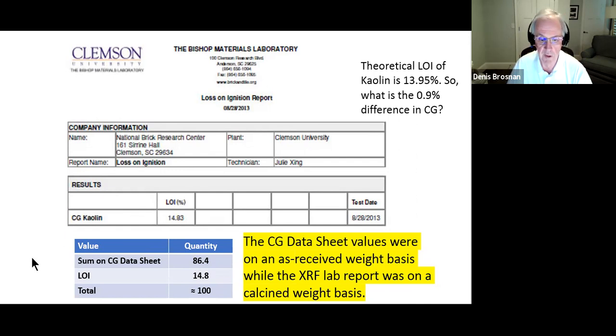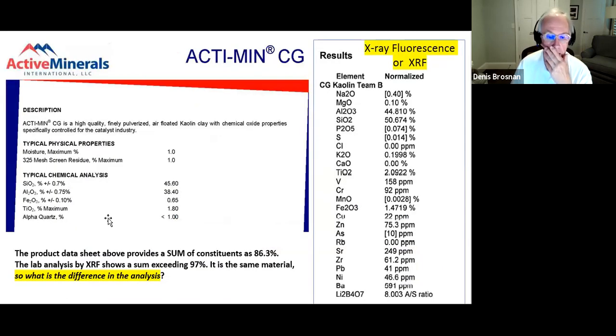So if you go back to the previous slide, the sum of all the minerals in the CG data sheet was 86.4%. If I add in my loss on ignition of 14.8%, then I come up with slightly better than 100%. So here's the deal. Back here, when we were looking at these product data sheets, the CG kaolin was expressed on an as-received weight basis, okay? Whereas the expression from my laboratory factored in the loss on ignition, and so my result is on an ignited weight basis, okay? Ignited weight basis or constant weight basis on heating.